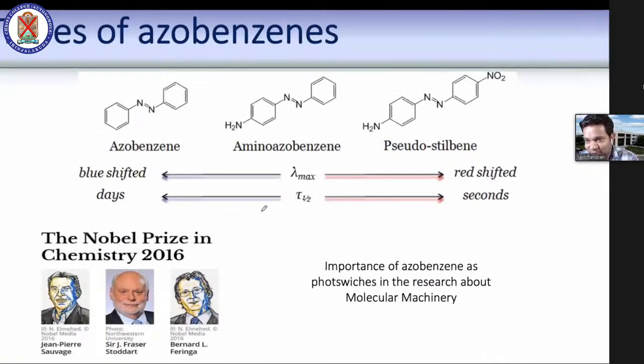When it comes to the types of azobenzene, we have three types: azobenzene, aminoazobenzene, and pseudostilbene. They go from blue-shifted to red-shifted, and the shelf life of the switching property goes from days in azobenzene, while for pseudostilbene it happens in seconds. This depends on the steric hindrance, the moiety we created, and the backbone of the structure.